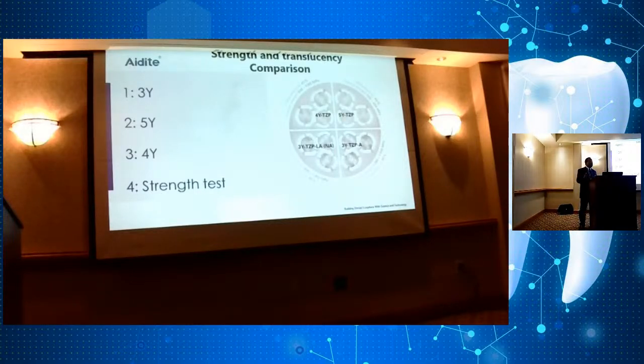So let's just say if you're doing an anterior case, older lady that doesn't have too many forces happening up front, it's okay to use a 5Y material. The limitation is going to be a 3-unit bridge. Okay, it's going to be mostly cubic material, but it's going to look okay. You have to be really careful with cubic zirconia because it tends to have a lower value. Okay, so some companies will make a 5Y zirconia, rated at 650 MPa.